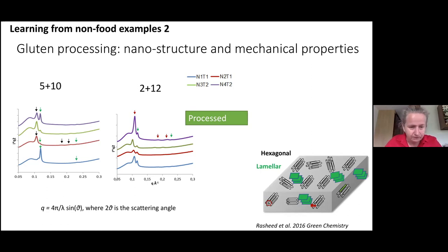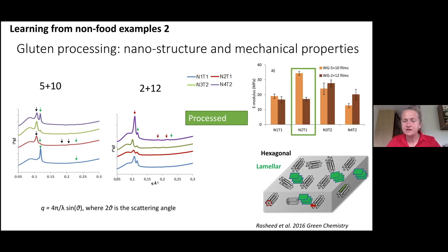So you see a lot of curves and a lot of arrows. I don't want to go too much into details, but on the left spectra, the red curve, you see the black arrows indicating hexagonal structure formation, while the green arrow is pointing at the lamellar structure. So in this type of system, we observed two different arrangements in gluten films. And of course, it is interesting how these structures correlate with the tensile properties. The one indicated with the bars shows a clearly different behavior in terms of the elastic modulus of these two films. So here's an example showing how genetics can play a role as well as the growing factors.